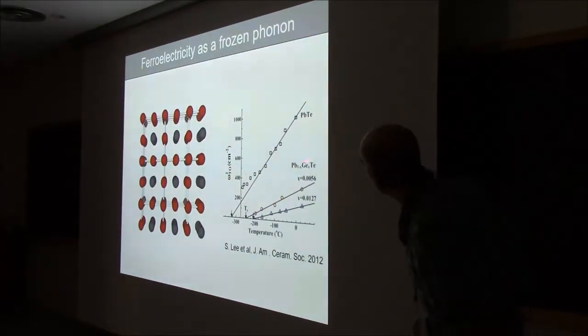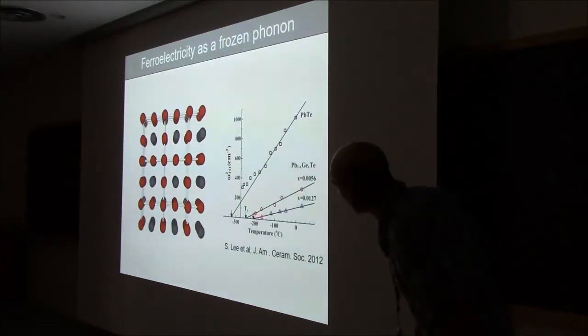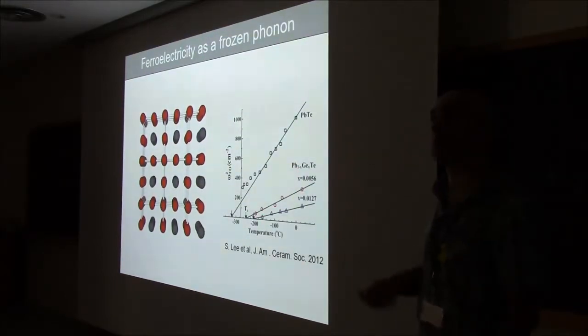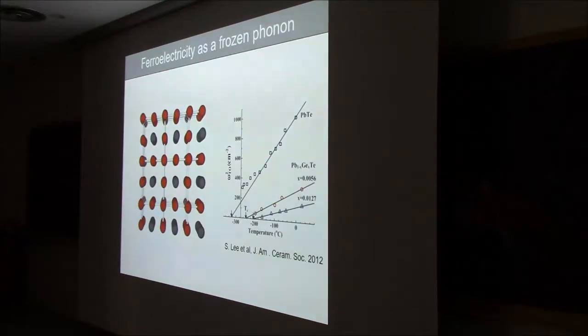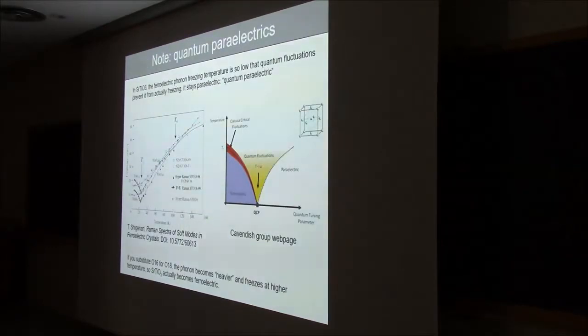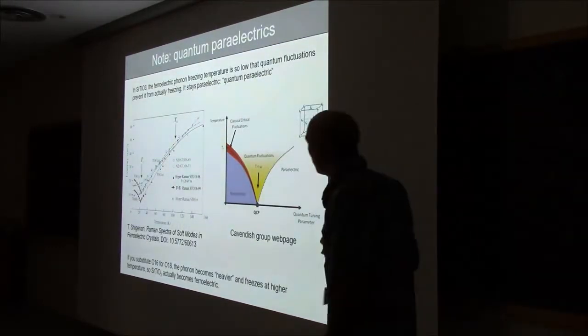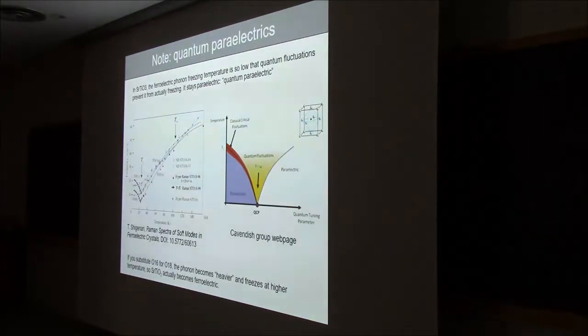But as soon as you mix it with germanium telluride, there's a finite temperature where things do freeze. Okay? So at least it's polar. Whether or not it's ferroelectric becomes a bit of a semantic question, because the standard definition of ferroelectricity is that something has to be switchable. The polarization has to be switchable, and if the material is very conducting, it's not trivial how to switch it. But, okay, at least it's polar. Questions? No questions yet. Don't worry, I'm going to make it even scarier. So I've been talking about this phonon freezing.